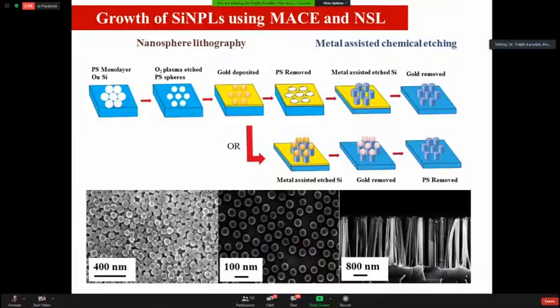All these 4 steps together are known as nanosphere lithography. After nanosphere lithography, we have a template of gold on top of the silicon substrate. So directly we place this gold template with the silicon substrate in a solution which contains HF, H2O2 and ethanol. Then it performs the metal-assisted chemical etching, and it forms the silicon nanopillars, which have the same dimension as the polystyrene nanospheres we used for making the template. So after removal of the gold, we have silicon nanopillars grown on the silicon substrate.